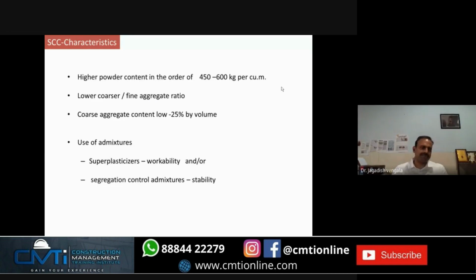We'll see all that. Okay, let us see some of the characteristics of self-compacting concrete when compared with normal concrete. Normal concrete, when it comes to cementitious content, varies between 300 to 450. We have seen that in the previous slide. But in self-compacting concrete, the minimum cementitious or powder content starts at 450 and is between 450 to 600 kg per cubic meter of concrete. In normal concrete it is 300 to 450.